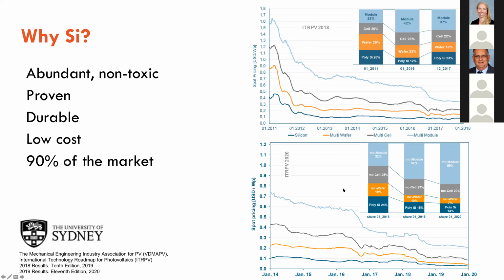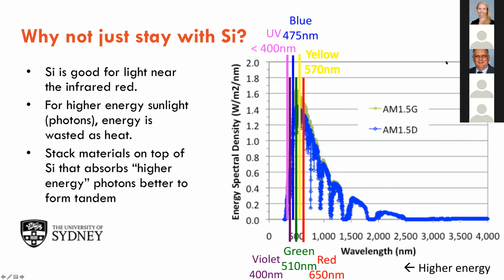So anyhow, the question is, why not just stay with silicon? You know, we're doing well, photovoltaics is cheap, everybody is putting it on their roof. 50% of the rooftops in some of the suburbs in Australia have got solar modules, and on average the nation has got 15% rooftop photovoltaics. So why? Well, that's because silicon has got one single band gap of 1.1 eV, so it's good at absorbing light near the infrared. It also absorbs light above the infrared, but if you remember, when a photon has an energy higher than the band gap, it does get absorbed, but what happens? It generates heat. So a lot of the energy gets wasted.